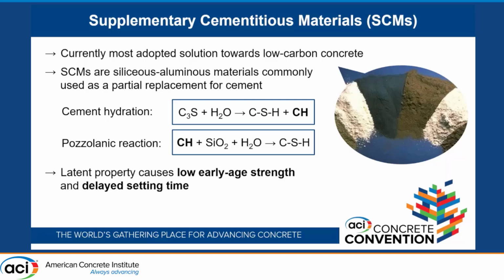One of the main problems we have with SCMs, though, is low early age strength and delayed setting time. Because the pozzolanic reaction just happens on a secondary base. So you have first the hydration happening, and then later on, the pozzolanic reactivity is going to catch on, and that causes a delay in your performance. So like I said before, we're also focusing on the performance, so we need to address that.